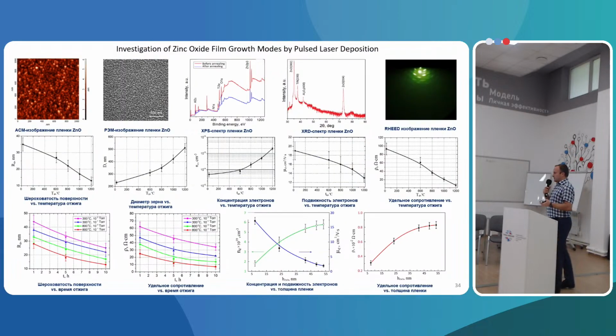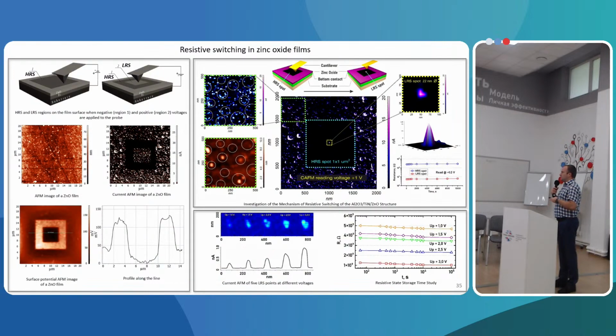We synthesize zinc oxide films by pulsed laser deposition and investigate the main growth parameters and growth regimes. We investigate nanoscale resistive switching on these films by scanning probe microscopy, by CAFM. We present the visualization of single current bridge and current AFM of writing processes and reading processes by CAFM.